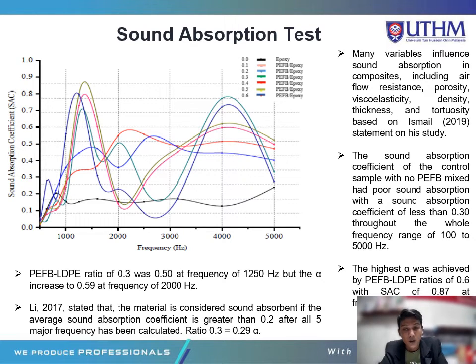The highest alpha was achieved by PEFB LDPE ratio 0.6 with an SAC of 0.87 at the frequency of 1250 Hz. PEFB LDPE of 0.3 was at 0.5 at the frequency of 1250 Hz, but the alpha increased to 0.59 at the frequency of 2000 Hz.